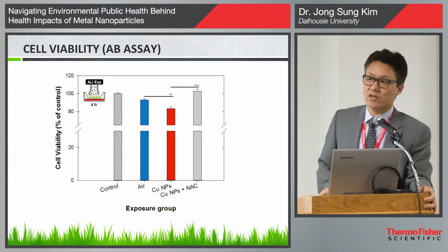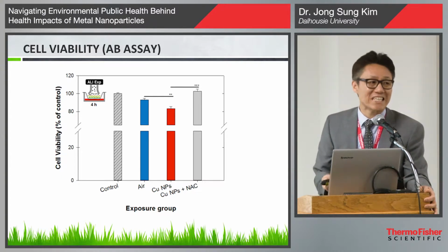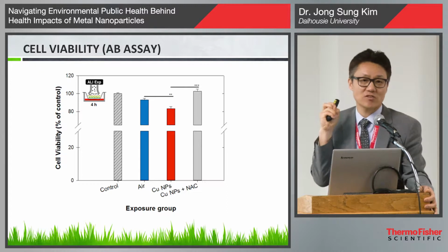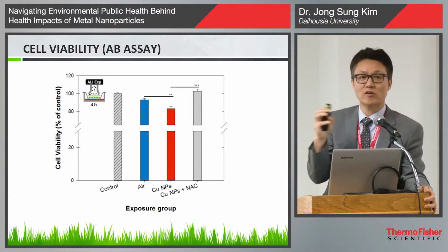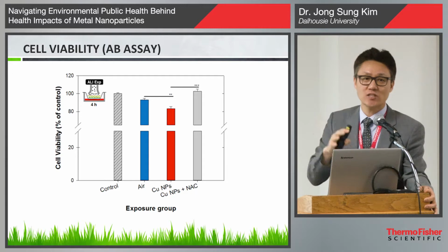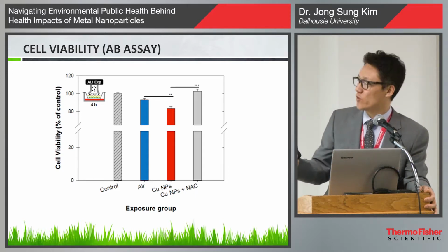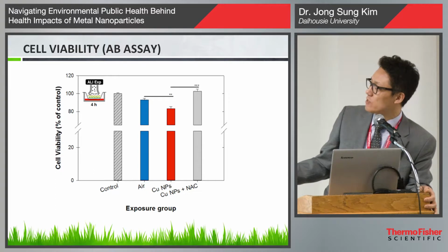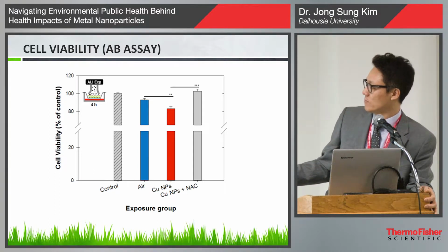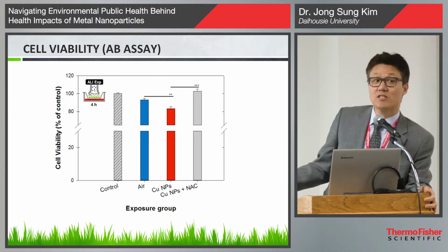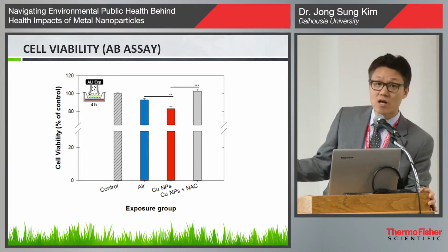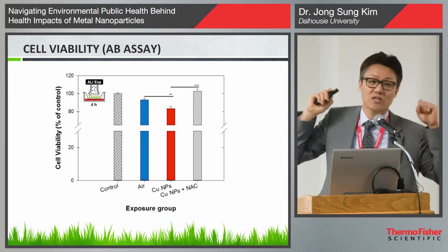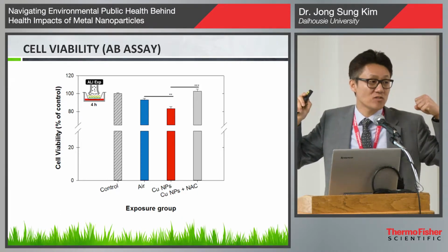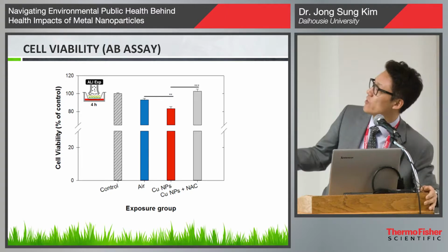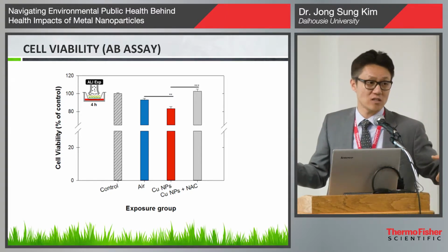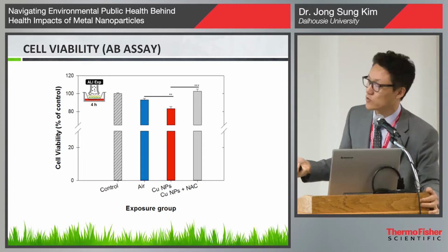NAC is N-acetyl cysteine, which scavenges reactive oxygen species generated by chemicals or nanoparticle. So we use NAC a lot to see how the system works. As you can see, copper nanoparticle exposure itself killed 20% of the cells. But when you add NAC, which removes the reactive oxygen species causing toxicity, you can see the cell viability didn't change. So the NAC system works well.